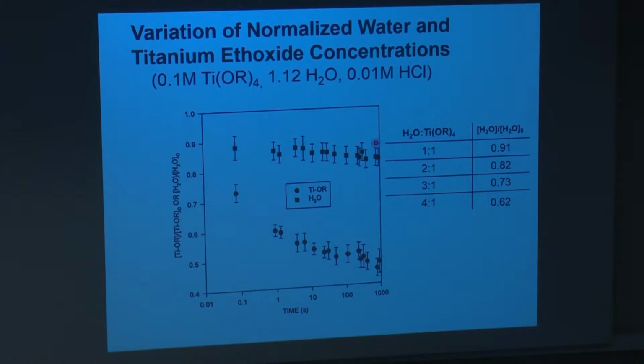We also looked at titanium ethoxide and how that concentration varied, both the water, shown here, and the titanium alkoxy ligand. As you can see, it does not decrease as quickly as the zirconium alkoxide. You can also see that the water continuously decreases, showing that you still have some hydrolysis occurring as well as condensation occurring in this particular system.